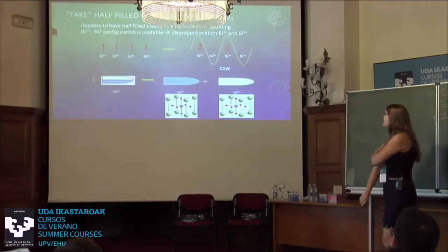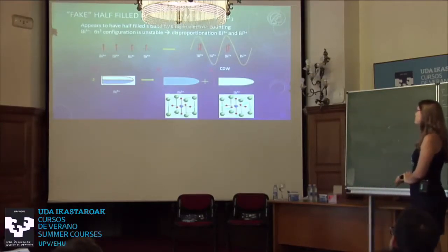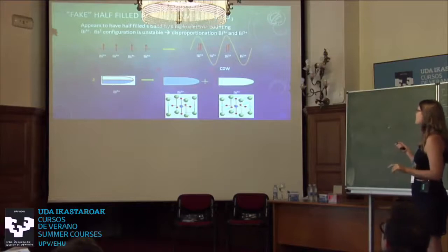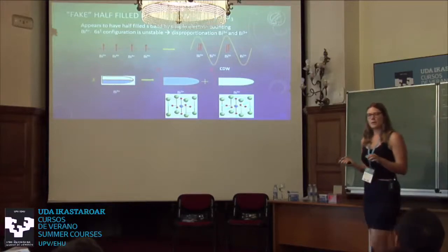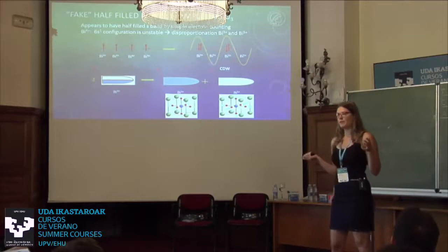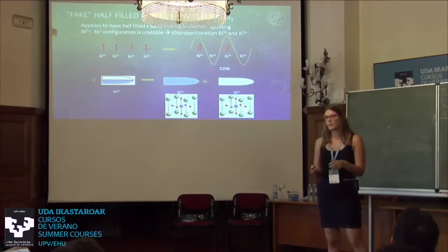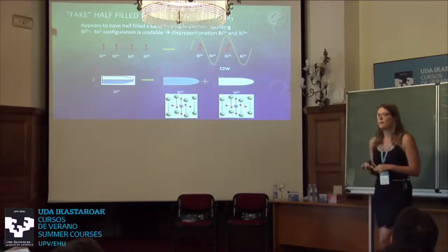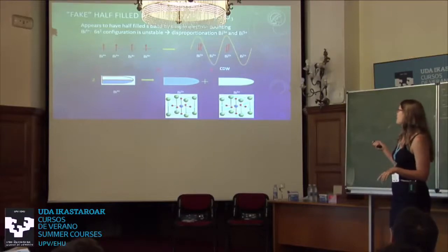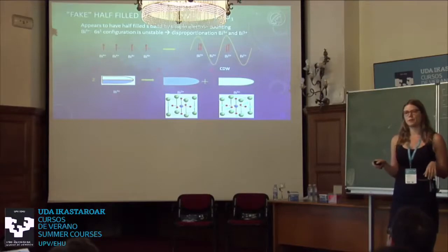And so here's another example about this bismuth 4+. There's a very famous compound, barium bismuth oxide, which maybe some of you who work on superconductivity know, because if you dope that with some holes, it becomes a 30 Kelvin superconductor. So this compound, if you would formally count the electrons, you would think you have a bismuth 4+ and a half-filled bismuth band.